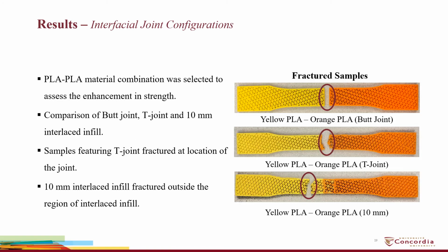In this first experiment, we used PLA material to compare butt joint and T-joint with 10 mm interfacial joint. Samples featuring butt joint and T-joint fractured exactly at the location of the joint, whereas the interlaced infill joint remains intact during the tensile test. This shows that interfacial joint is at least as strong as other infill regions in the sample.